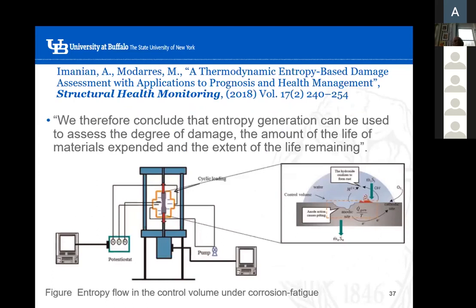This is a work by Professor Mohammed Modarres at the University of Maryland in College Park, where he uses this theory for predicting corrosion fatigue. So in the experiments, they have samples, they subjected them to corrosion and also fatigue. This is the setup they have, where the sample is subjected to fatigue and also corroded. They conclude that entropy generation can be used to assess the degree of damage, the amount of the life of materials expended, and the extent of the life remaining.